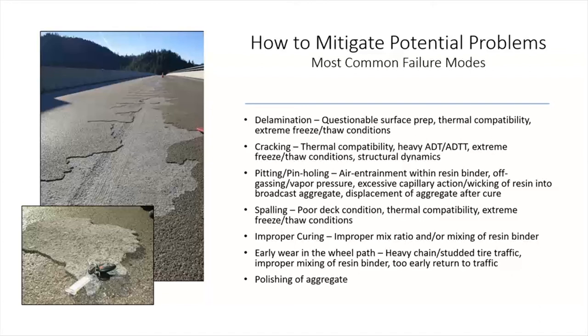The resin binder is lower in viscosity, and when you have aggregate thrown into that resin binder, you have this capillary action. It's like a wicking. The finer the gradation of the aggregate, the more wicking action you're going to have. And you start wicking up more of that resin binder, and then you can have some pinholes. The other thing that can happen when it's cold is you have a lot of chains and studded tire traffic, and the resin binder becomes more brittle over the years and more brittle in cold temperatures. Heavy loads can impact the individual aggregates, and you can have pop-out aggregates, and it appears as pitting over a period of time.